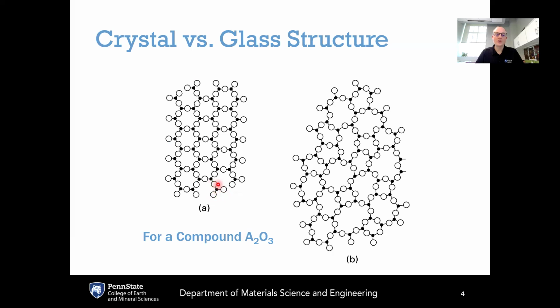And then you'll note that each one of these oxygens is bonded to 2 cations. So every oxygen here is bonded to 2 of these cations A. And this is what gives us the basic structural unit of this crystal. And this basic structural unit of the crystal is identical to the basic structural unit in the glass.